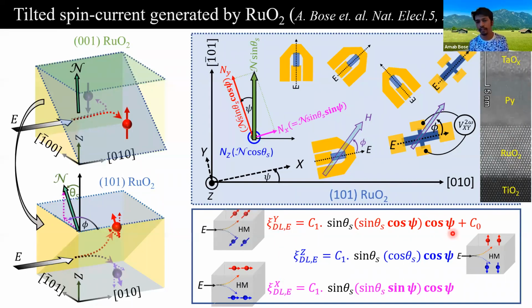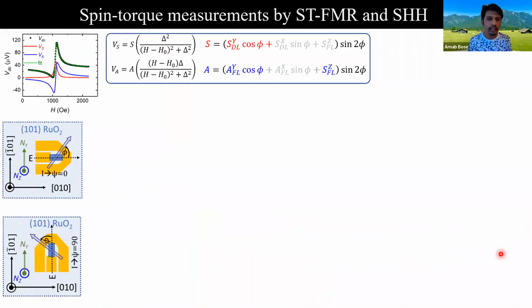The y component should have, again, I'm repeating, cos square. The z component spin torque should have cos psi, and the x component spin torque should have sin 2 psi. This is what we want to experimentally measure as a probe for the spin split bands of ruthenium dioxide. Now, let me show you some experimental data.